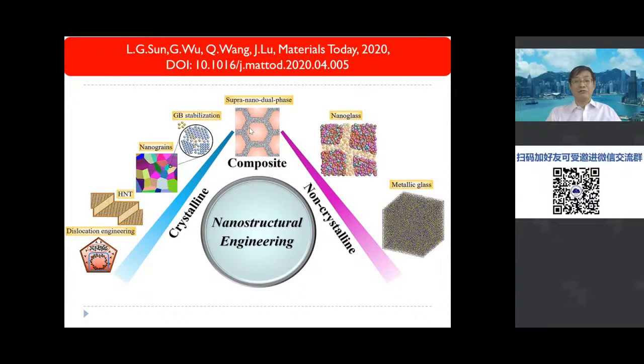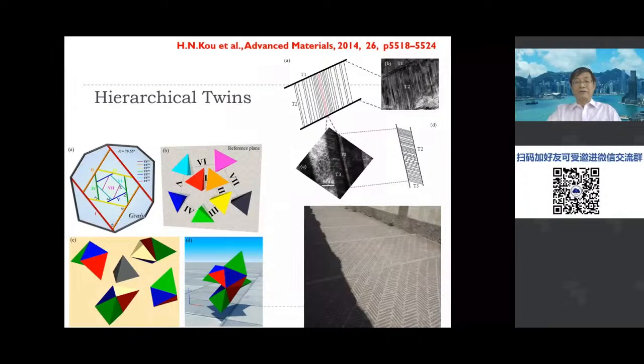That means the two phases are smaller than 10 nanometer. Of course, as a metallic material or crystal material, we always have a grain boundary stabilization problem with nanograin when the grain size is very small. And also we have other types of defect to be managed, such as hierarchical nanotwin, or we can also engineer the dislocation. So these are major trends for the development of a new structural material with a crystal structure or amorphous structure. So for the nanotwin, basically what we try to do is to enhance the nanotwin density inside of the structure.